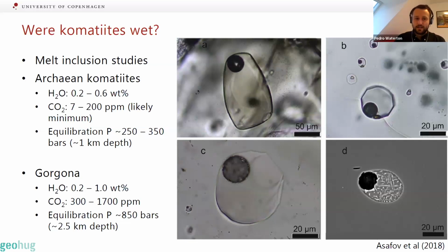So looking at Archean komatiites, most of the published studies find that there is some water in these, and it's between about 0.2 and 0.6 weight percent. In terms of CO2 contents, there's not very much CO2 at all, 7 to 200 ppm. But this is likely a minimum because CO2 begins degassing at such high pressures, compared to water, so they probably lost some. And when you calculate equilibration pressures for these, you get about 1 kilometer depth. Gorgona, which is the only widely accepted Phanerozoic komatiite, has higher water contents between 0.2 and 1 weight percent, and more CO2 between about 300 and 1700 ppm, with an equilibration pressure of about 2.5 kilometers.